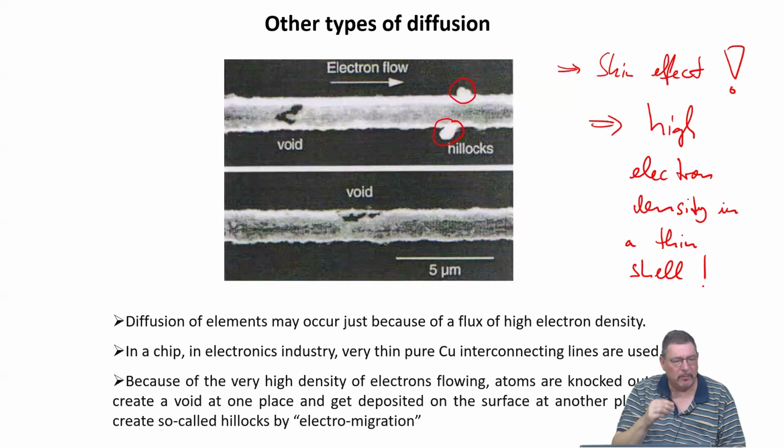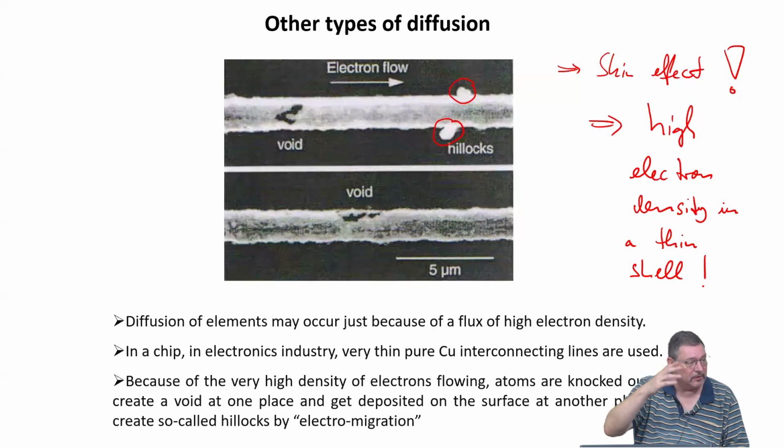And at some point, maybe there was a small crack or a small imperfection in the wire, and there they aggregate, so they grow a new crystal, they find a new position, and this is then often causing mechanical instability, or maybe because of the electrical field and instability, you can get a shortage with neighboring wires.